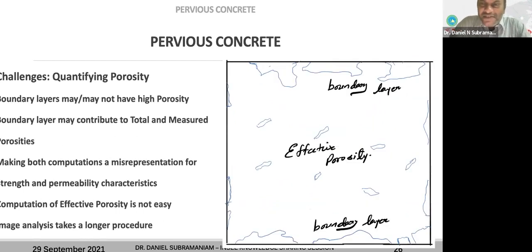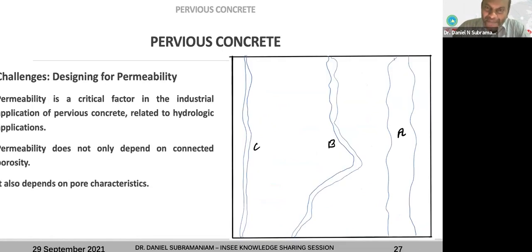And then after that, this is also something that we found out in our research, that there is a boundary effect. So if you take the total porosity, say, for example, it's going to be about 0.3. But what we found out is that of the 0.3, the major fraction of the pores are actually on the sides, in the boundaries. So what you have in the middle is significantly less, say something around 0.2. That we call the effective porosity, and the other one we call the porosity in the boundary layers, right?